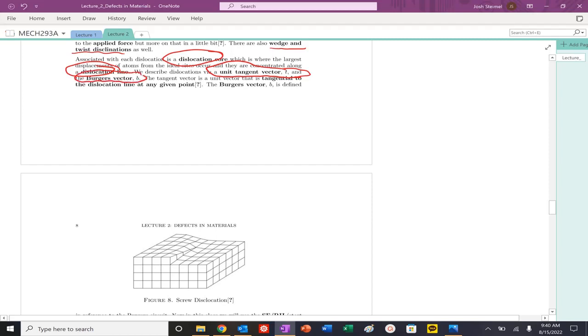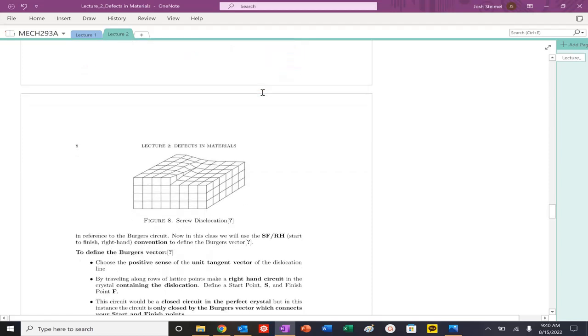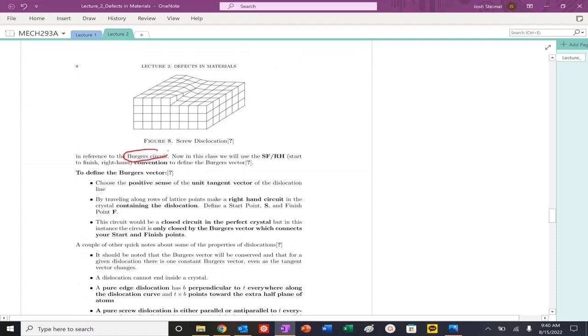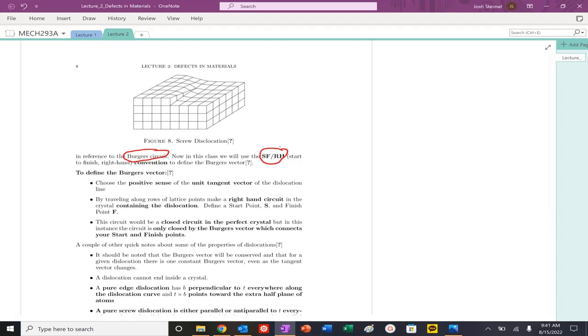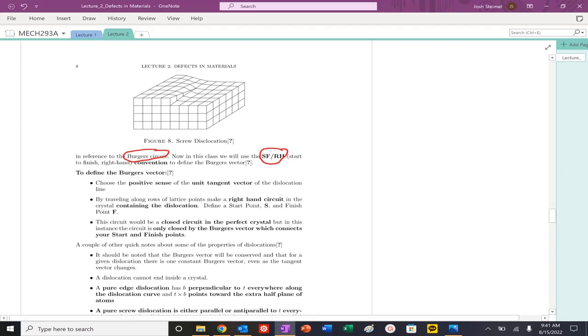It's also described by Burgers vector. The tangent vector is always tangent to the dislocation line. The Burgers vector we will define by drawing a Burgers circuit. There's lots of different ways you can define a Burgers circuit. In this class, we will be using the following notation. If you see something different, the Burgers vector should always be conserved. Whatever method you use, you should always have the relationship. If the relationship between the tangent vector and the Burgers vector is perpendicular, that is an edge defect or edge dislocation.